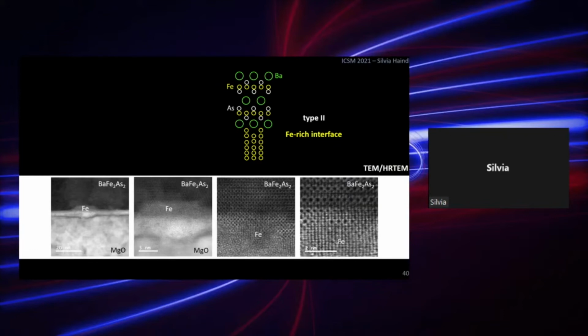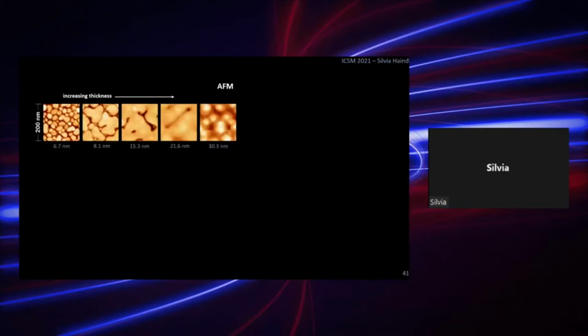So I will now show you how this heterogeneous interface is changing the film roughness when we increase the thickness of the films. You see here a thickness series of 5 films, and here the AFM images of the surface topography. What we can see for the very thin film is that we have a very strong island formation, whereas after a certain threshold thickness of 30 nanometers, the film seems to be continuous, and the surface roughness is governed by mound formation of the multilayer growth.